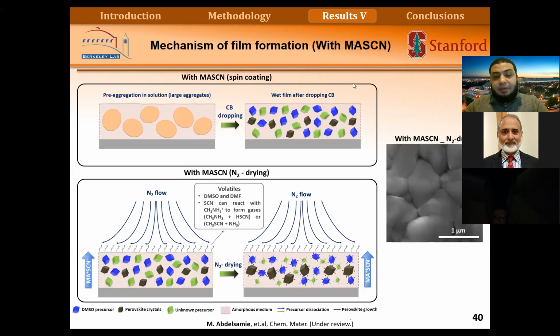But if we use additives, what we have found is that we have large aggregates in solution, and these large aggregates lead to larger crystals in the as-cast film, as we can see here, and also lead to lower nucleation density. And as we apply nitrogen drying, we remove the volatiles from the top surface, and this leads to MASCN, which is the additive, diffusing within the film. As it diffuses, it reacts with the intermediate phases and dissociates them, which helps to grow the crystals. So during the nitrogen drying, we have found that the MASCN interacts with the intermediate phases, and we found two different intermediate phases here. One is unknown, and one is an intermediate phase with DMSO, which is one of the solvents that we use. For both intermediates, we found that MASCN can dissociate both of them very quickly at room temperature, and after dissociation, they contribute to the growth of the perovskite phase. This happens at room temperature and leads to the formation of very large crystals.